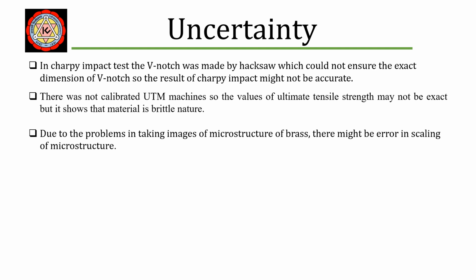In all the testings, there were some uncertainties, so the results might not be accurate. But the trend of results shows the brittle fracture nature in the tensile and compression testings. The uncertainty is as follows. In the Charpy impact test, the V-notch was made by hacksaw, which could not ensure the exact dimension of the V-notch, so the result of the impact test might not be accurate. There was no calibrated UTM machine, so the values of ultimate tensile strength may not be exact, but it shows that the material is brittle in nature. Due to problems in taking images of the microstructure of brass, there might be error in scaling of the microstructure.